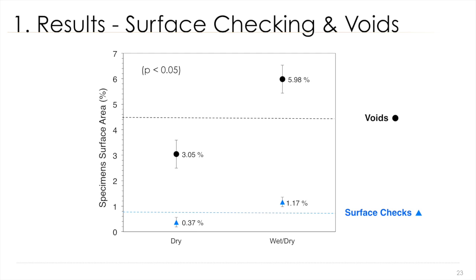This graph shows the average checking and voids from 6 replicate samples from different panels. Checking increased significantly threefold, and voids increased significantly twofold. The average irreversible thickness swelling for the 6 replicates analyzed with this method was around 16%.